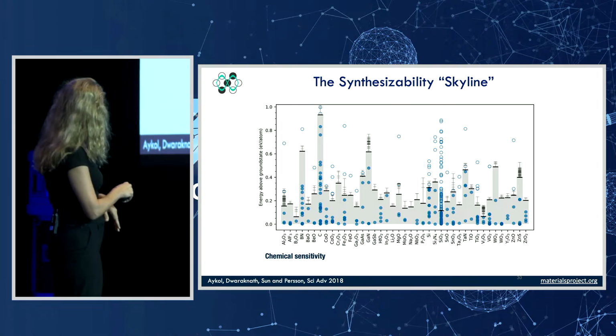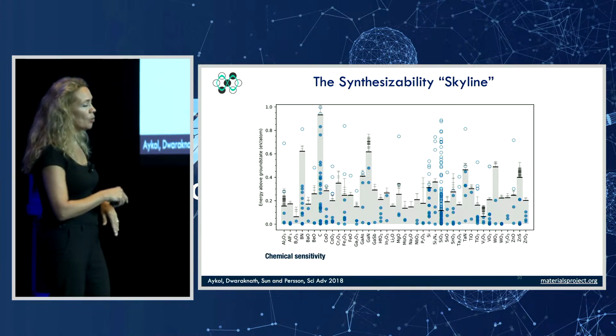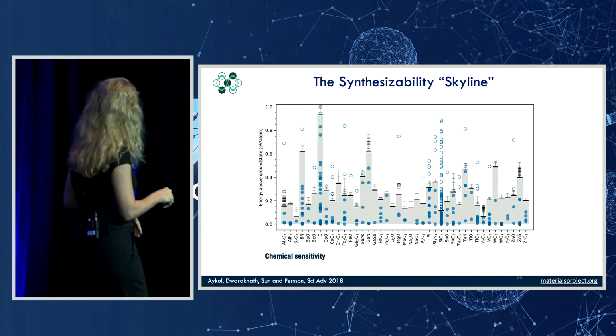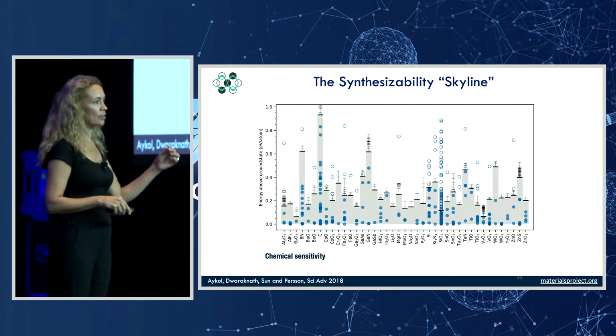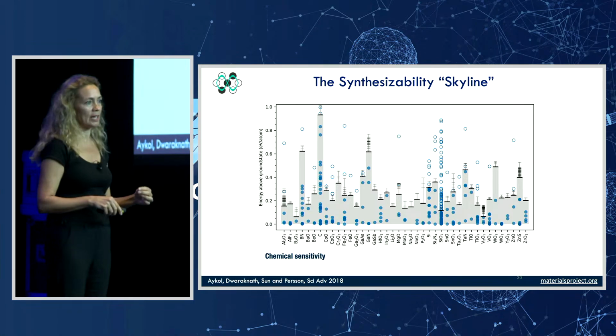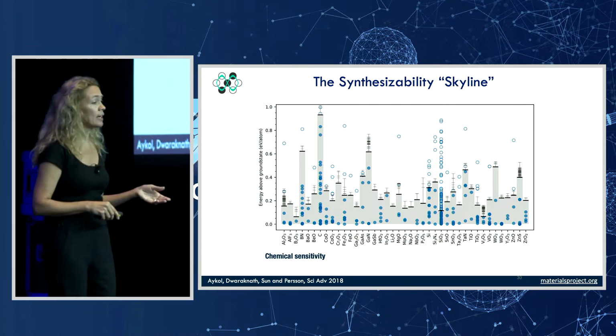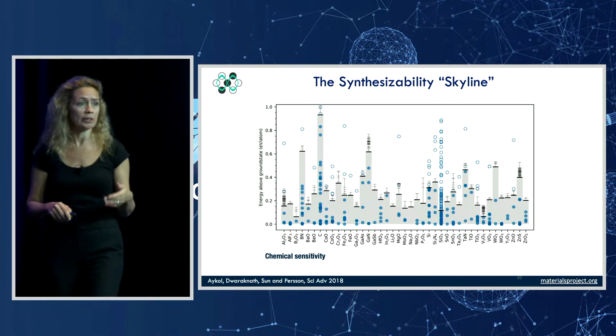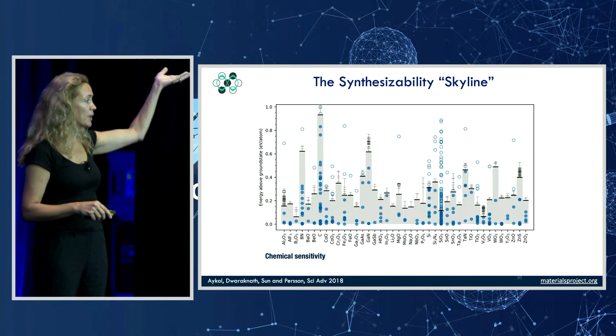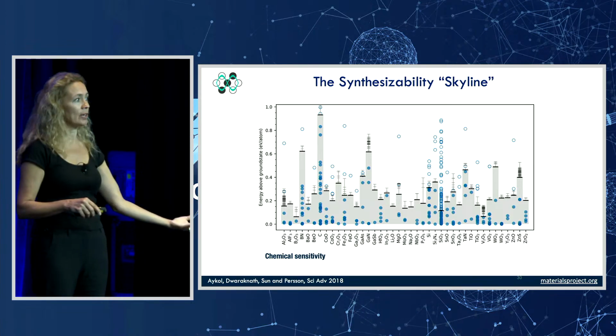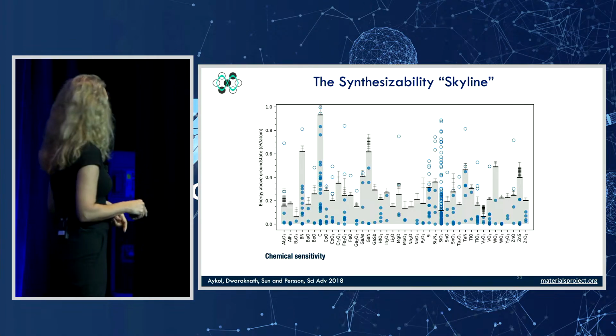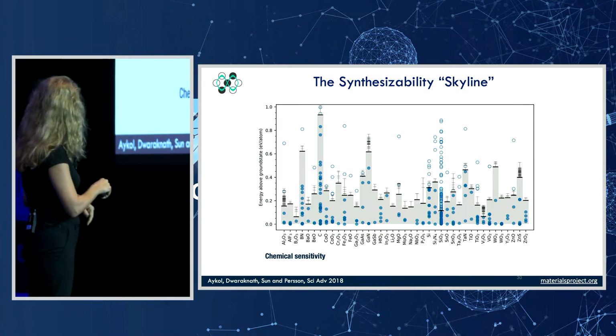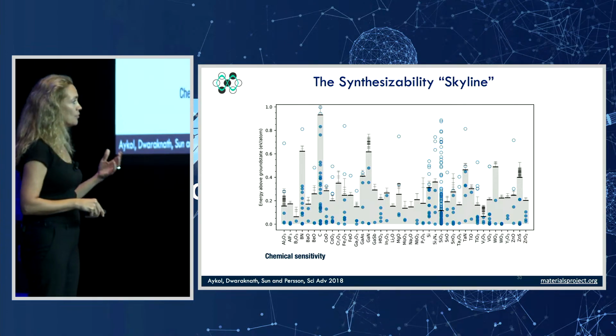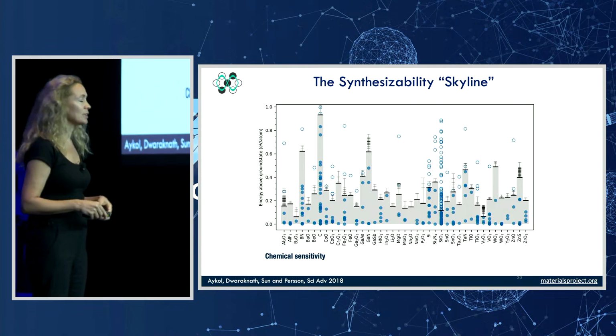And these are set by all these bars. And as you can see, they vary quite a bit in energy above the ground state. So anything from like 100 meV up to almost 1 eV. So very, very variable. And the filled circles are materials that have been made and that survive at ambient pressure. So they're real materials. And the empty circles are materials that either have never been seen, they're in the Materials Project, they're hypothetical materials, or they have been made at high pressure, but once we bring them down to ambient pressure, they amorphize. So they're not stable at ambient pressure. And as you can see, there's not a single system, even though this amorphous limit varies quite a bit, that violates this rule. So we do believe that it's real.